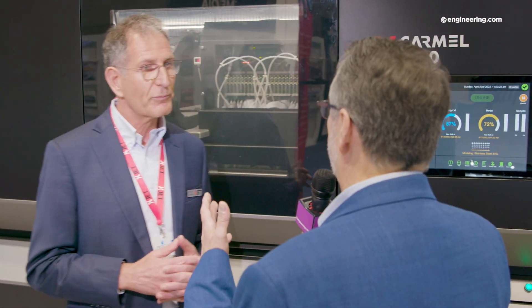The process is really straightforward: you print and build parts quite quickly at 10 micron layer thickness, take the tray, place it into our support removal system, and then the parts go into sintering. With relatively low shrinkage — 14 to 15 percent — you get a final part with super high density, over 99 percent density.